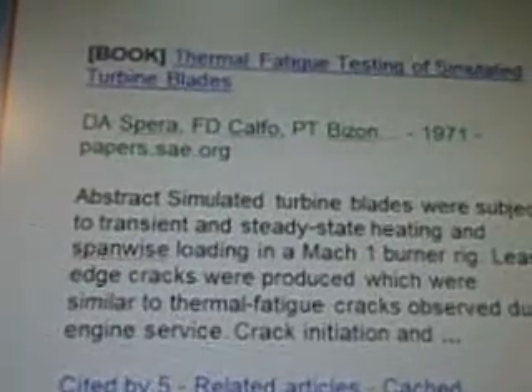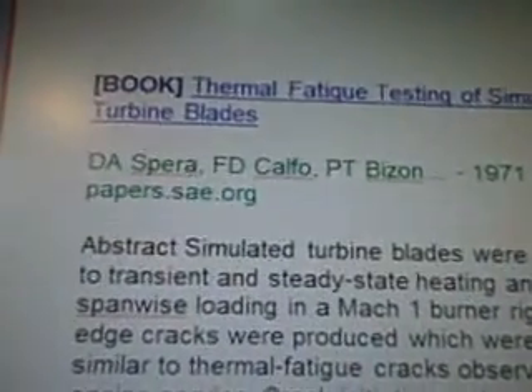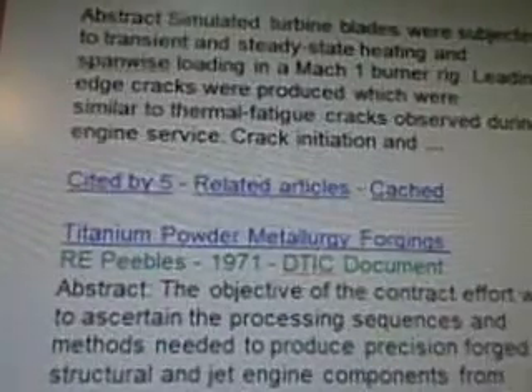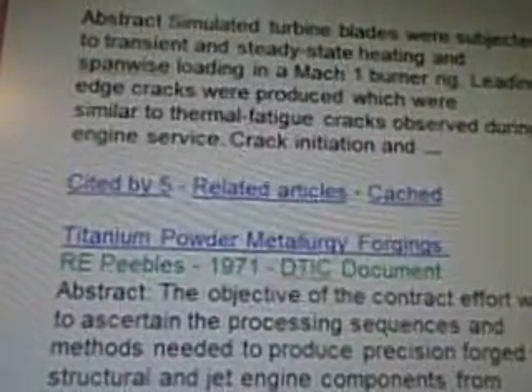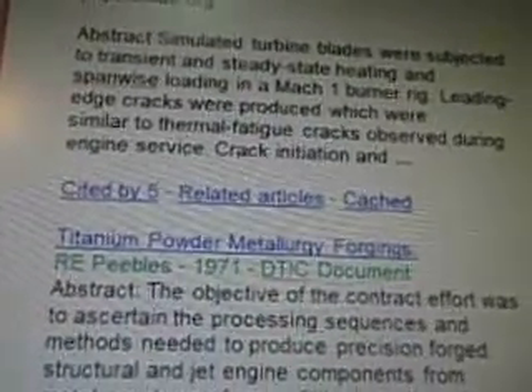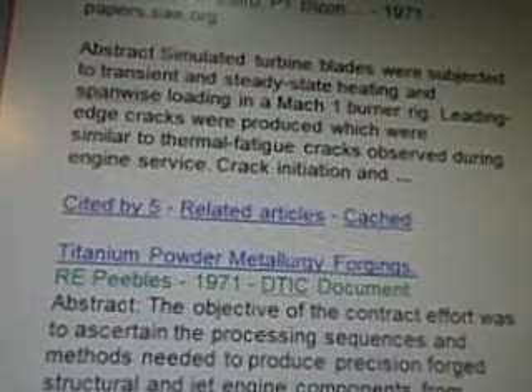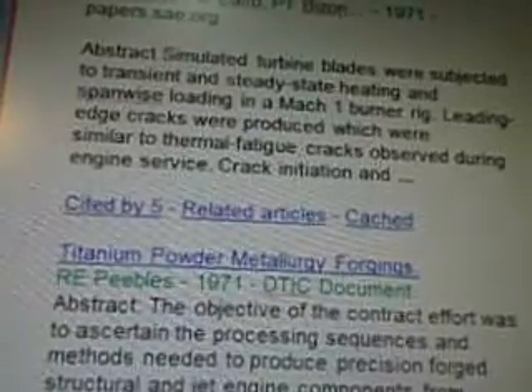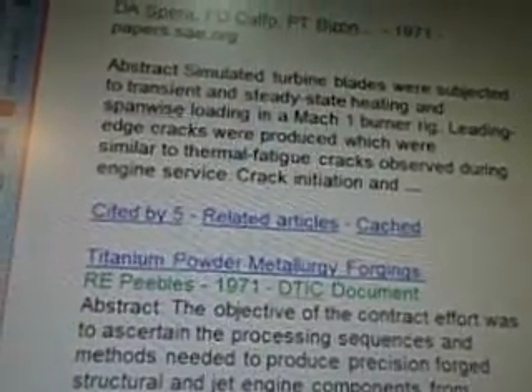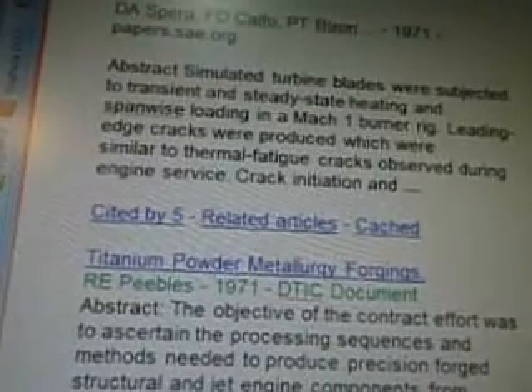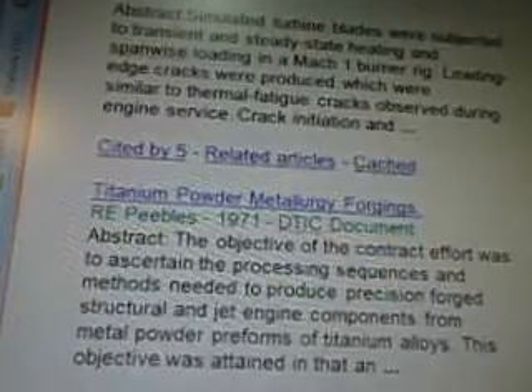And it says thermal fatigue testing of simulated turbine blades from D.A. Spera, 1971. Abstract: simulated turbine blades were subjected to transient and steady-state heating and span-wise loading in a Mach 1 burner rig. Leading-edge cracks were produced, which were similar to thermal fatigue cracks observed during engine service.